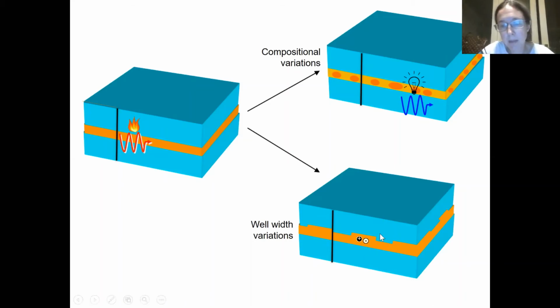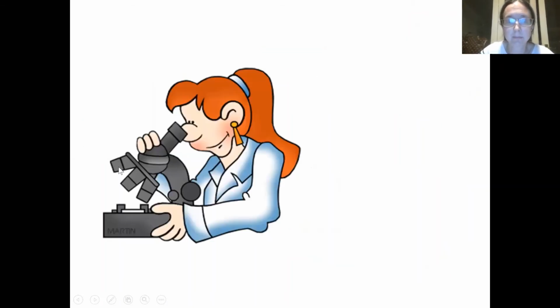So it could be that the electron and hole get stuck in a wide bit, which also turns out to be a lower energy place for them to sit than the narrow bit of the quantum well. And again, there are barriers to them exiting this wide bit of the quantum well, so they don't go to the defect, they recombine, and they give out light. So those were the two hypotheses that people had about why indium gallium nitride quantum wells were really robust to the presence of these defects.